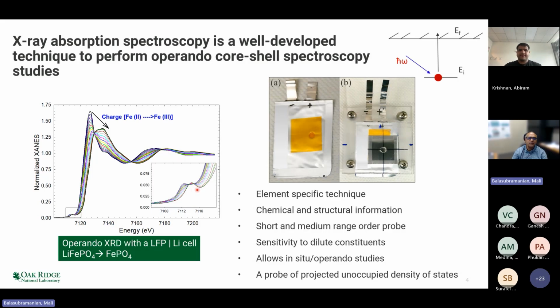And so you can directly probe those unoccupied density of states, either by means of a dipole transition, where the 3D orbitals mix up with p-like orbitals because of symmetry considerations, or through quadrupole transitions, which are not dipole allowed, but are weakly quadrupole allowed. So you can look at those direct transitions of the unoccupied density of states through X-ray absorption spectroscopy.